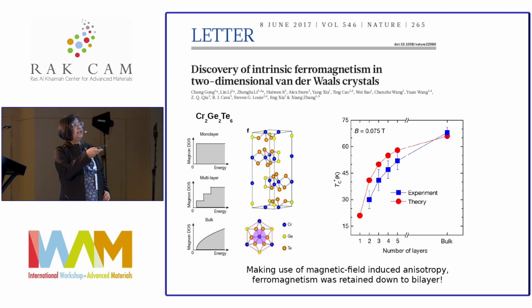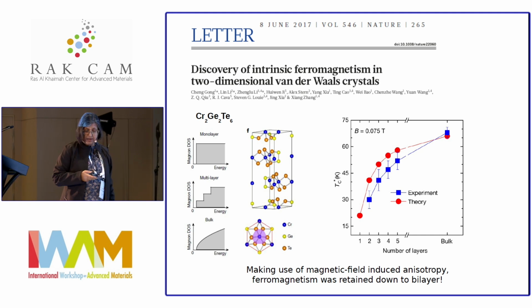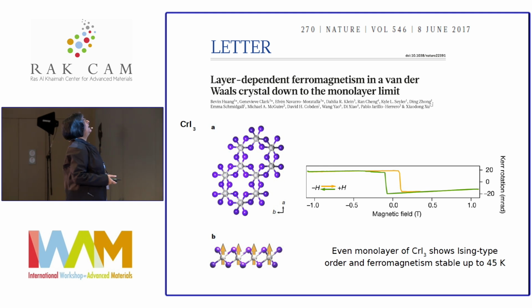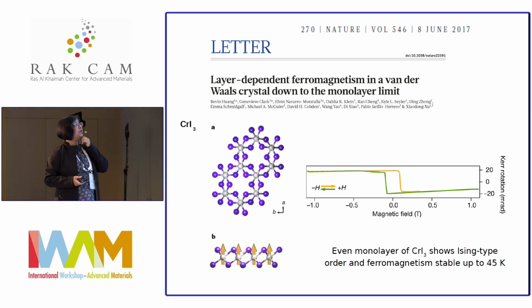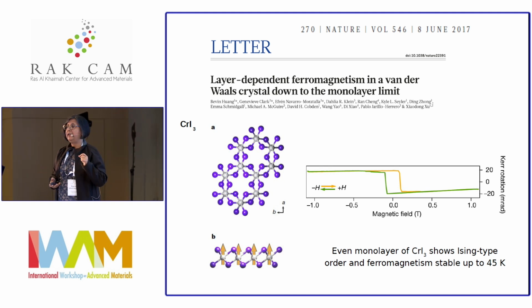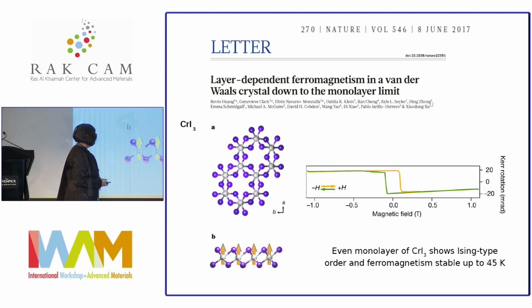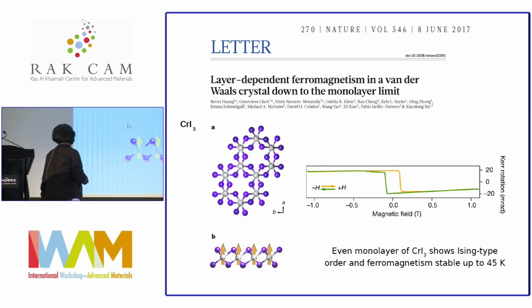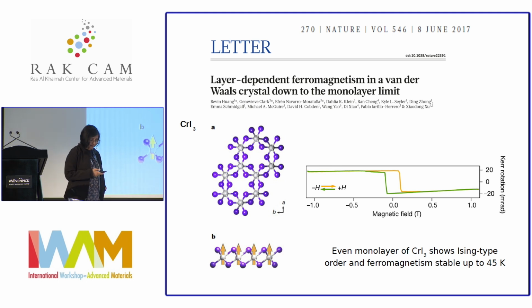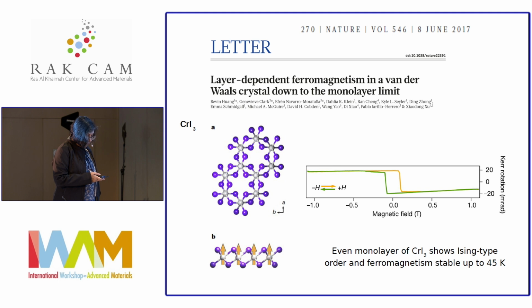And theoretically, they could even show that even at the monolayer limit, it's actually a ferromagnet. And the other one, chromium iodide, experimentally, at the monolayer limit, actually shows Ising-type ferromagnetism, stable up to 45 Kelvin. So that has a lot of technological importance.